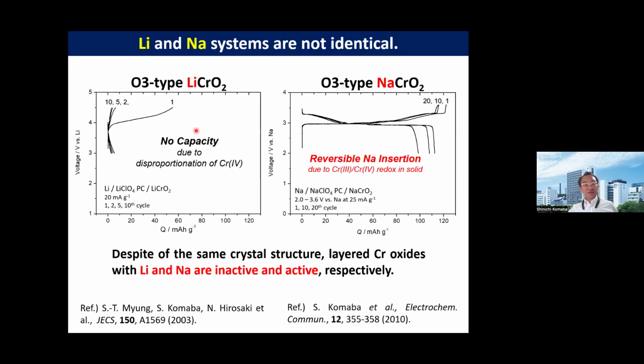Not only cobalt, we can also compare the chromium case for lithium and sodium. It was so surprising that for lithium chromium oxide, the reversible capacity is negligible, but in the case of sodium, it is highly reversible at around 3 volts. So the message is that even for an element that is electrochemically inactive in lithium, we should test the similar sodium cases. Then we expect very different chemistry, different from lithium chemistry.